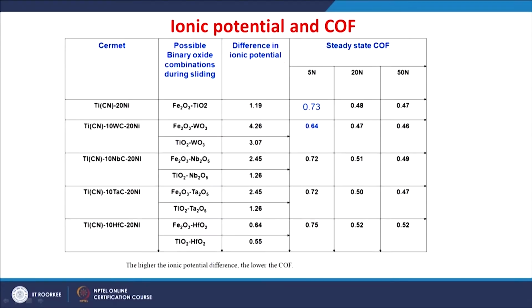So, based on this we again understood the steady state coefficient of friction with respect to the possible binary oxide combinations during this sliding and the difference in their ionic potential. So, you can see the formation of these possible oxides like iron oxide or titanium oxide are possible with the baseline cermets, whereas in addition to that, iron oxide tungsten oxide or titanium oxide tungsten oxide combinations are also possible in this particular cermet. So, we have actually listed down the possible binary oxide combinations during the sliding of these respective cermet materials, and the differences in their ionic potentials are also listed.